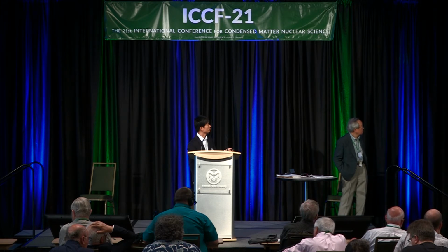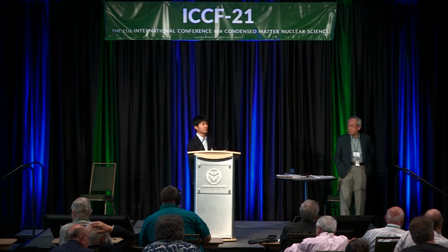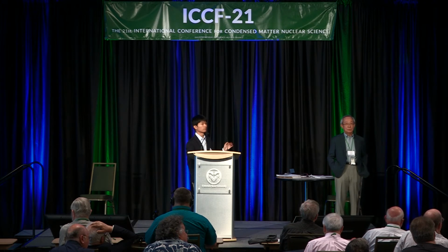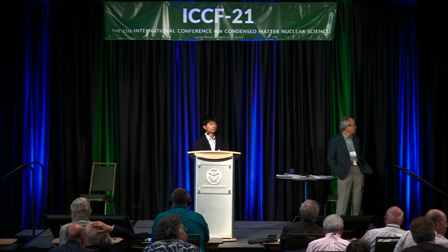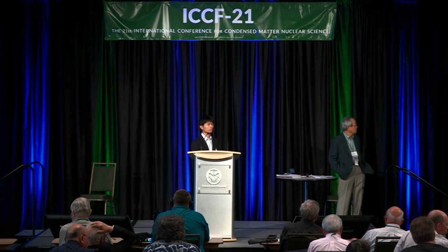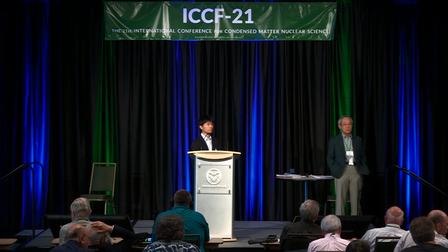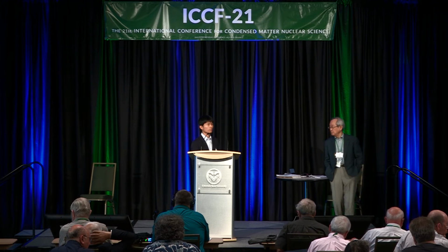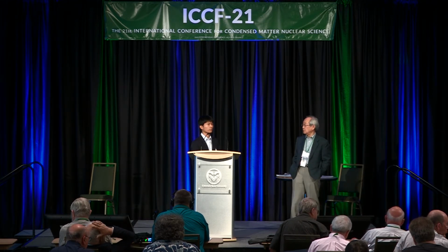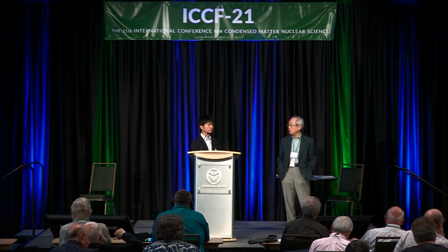You mean the decay rate? No, the gold that you've got on there would act as a neutron witness material. It would activate, and you would see a 412 keV gamma line with about a 2.7 to 2.8 day half-life. And it has a reasonably high capture cross-section in barns.